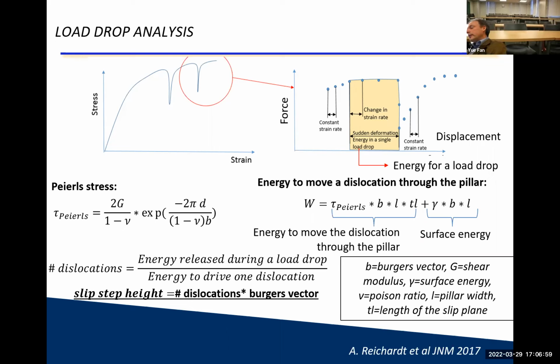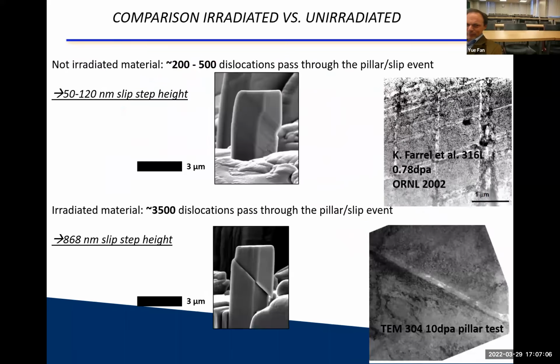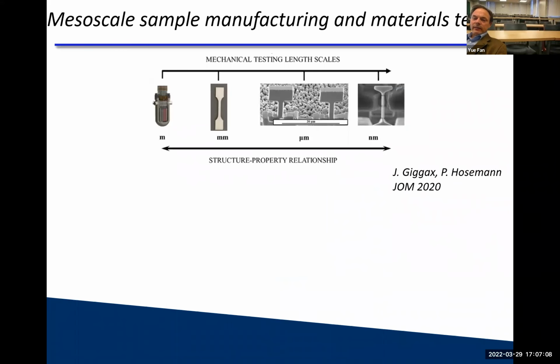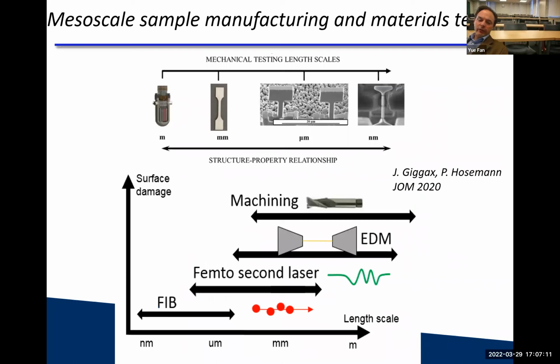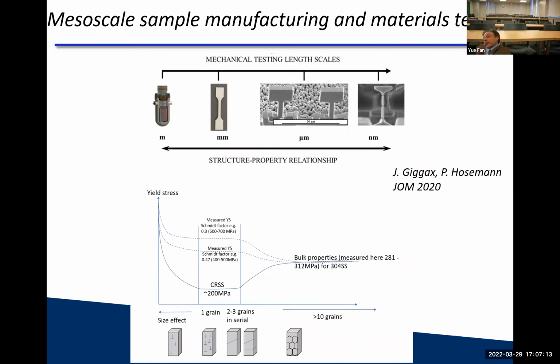If you want to, then you have to consider, of course, the grain size and what is the strength. The way I like to say it, grain size is maybe not the best way, but what is the strength determining feature I'm actually after? That may sometimes be the grains, sometimes precipitates, sometimes radiation damage, depending on what that is. That may change the length scale by which you get bulk properties. So this is from a little while ago, but here's the length scale versus the yield strength, right? This is the typical size effect.